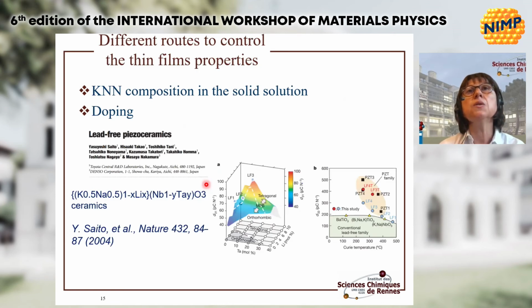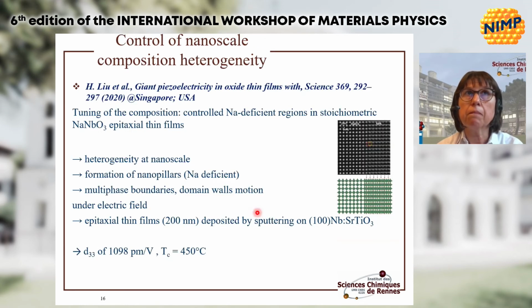Concerning the composition in the solid solution, by adding doping, Saito reported some years ago that it's possible to obtain different and high piezoelectric coefficients, as you can see here, in comparison with different other piezoelectric systems. So it's possible to change essentially the transition, and here we can see the morphotropic phase boundaries that can be controlled between tetragonal and orthorhombic phases by tuning the composition.